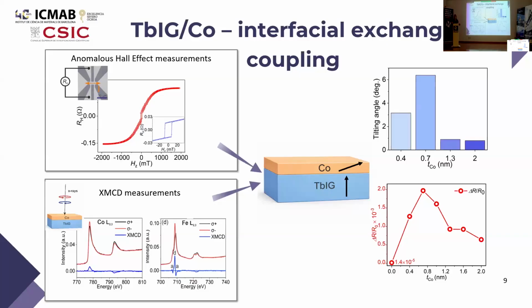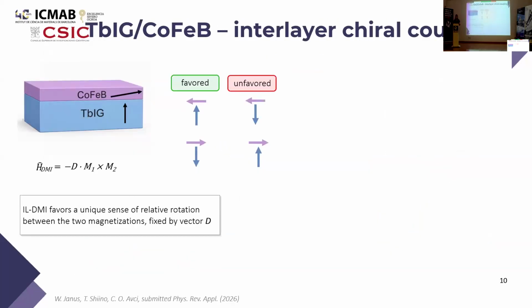After that, we wanted to check what is behind this increase. So we performed some additional electrical measurements and also some synchrotron measurements at the Alba synchrotron. With this, we found that in such a bilayer, we have some interfacial coupling between the perpendicular magnetic anisotropy in the garnet and the magnetization in the ferromagnetic layer. This coupling caused the magnetization of the ferromagnetic layer to tilt away from the surface, meaning that we have some small out-of-plane component of the magnetization. And if we look at the tilting angle as a function of the thickness of this layer, and compare with the magnetoresistance signal, we can see that this increase in magnetoresistance is directly correlated with this perpendicular component of the ferromagnet magnetization.